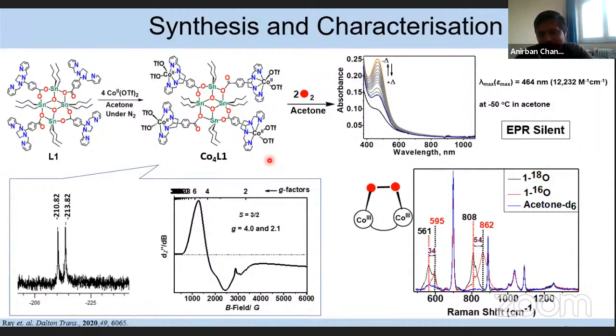I didn't check whether it's possible, because when I add an excess amount of proton to the cobalt peroxide, as I showed you, this peroxo band completely decays during the oxygen reduction reactivity. If it had to form a hydroperoxide, it should be stable at some point. Otherwise, if a proton comes and binds to form some kind of hydroperoxide, it can completely break the peroxo band and it drastically decays. And I don't think it would then react with increasing amounts of substrate and give a linear correlation of the k2 value.